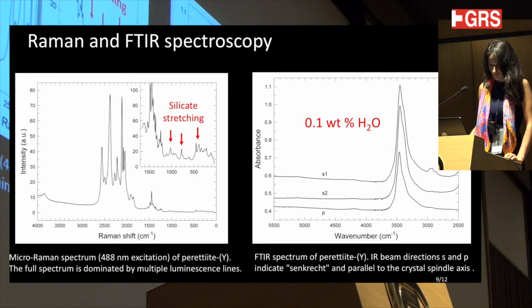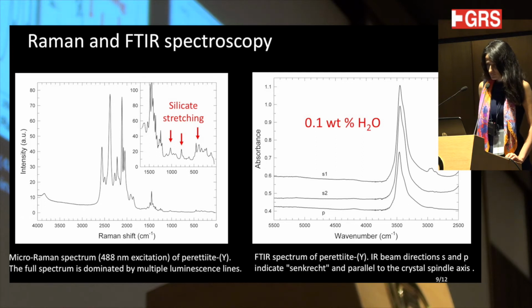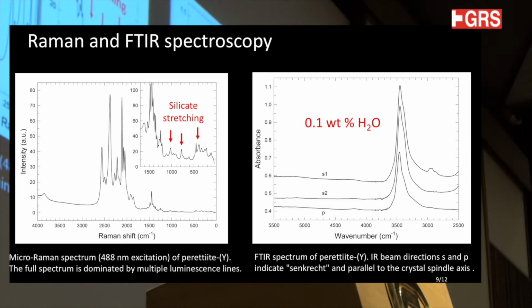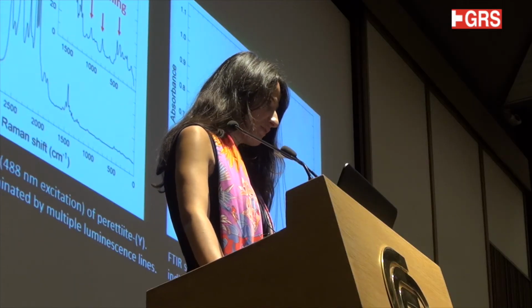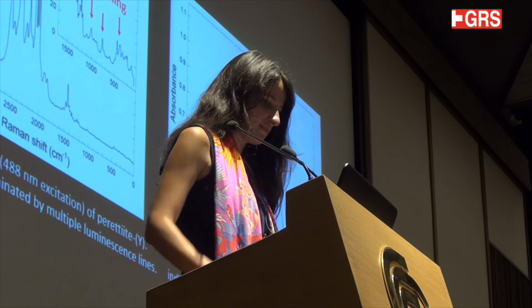We performed also FTIR spectroscopy, and we can recognize very intense absorption band in the characteristic OH stretching modes. With the correlation by Libowitzky and Rossman in 1997, we were able to give a quantitative content of H2O in the mineral, and it was around 0.1 weight%, so quite negligible.